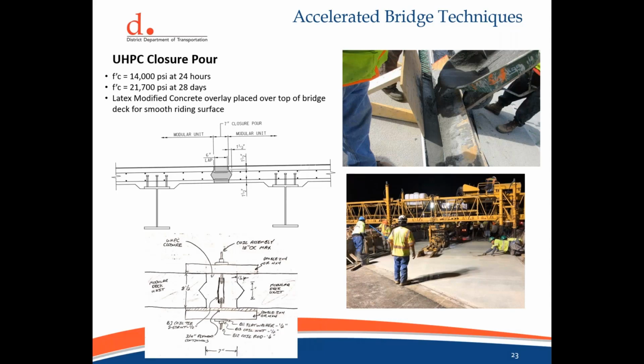The lower left detail is a formwork detail for the closure pour. This consisted of a coil rod assembly on the top and bottom with timber formwork. The coil rods were ultimately removed, and we had the contractor fill the coil rod voids with epoxy grout.